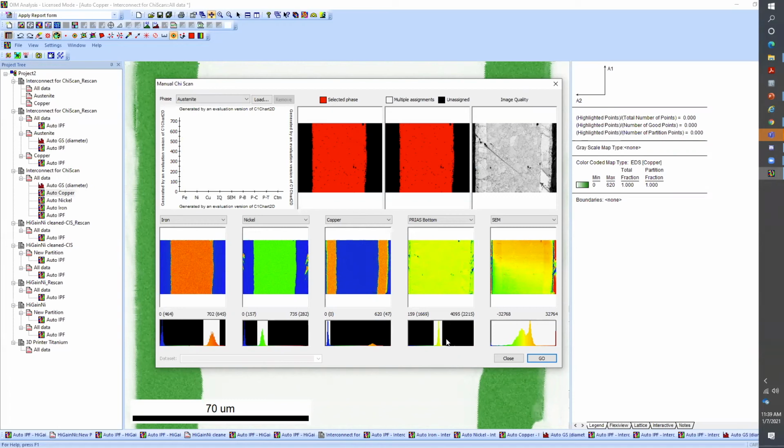I honestly usually use this for geological samples because it's quicker, to be honest with you. Because with the PCA, if I have a sample with 5 mineral phases in it, and those mineral phases share 3 EDS signals, but the actual component that matters is a trace element, doing the PCA and pulling those apart is very, very time consuming. So it's one of those things.